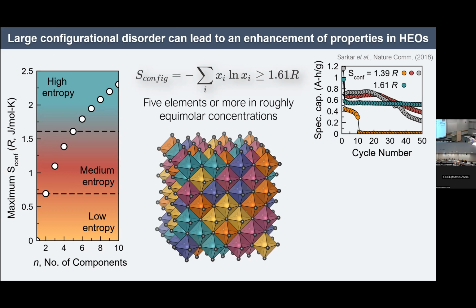Another set of explanations comes from different functional property measurements. This is an example of high entropy materials that have been fabricated into a lithium-ion battery. We're looking at the specific capacity, how much charge the battery can store, as a function of cycle number. The legend is a little bit covered, but the gray, red, and yellow cathode materials all have 4 components, and only the turquoise one has 5 components. Its stability as a function of cycle number is very robust, whereas the other 3 all fail in relatively short order, meaning that somehow this material is better able to withstand this violent lithiation and delithiation process. So there does seem to be some entropy stabilization effect, and that's a common theme in the field.